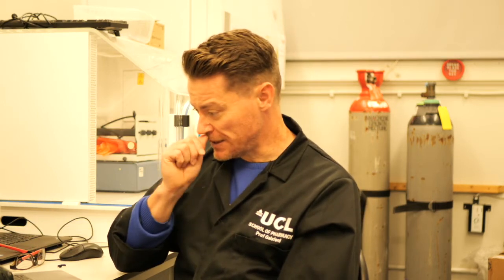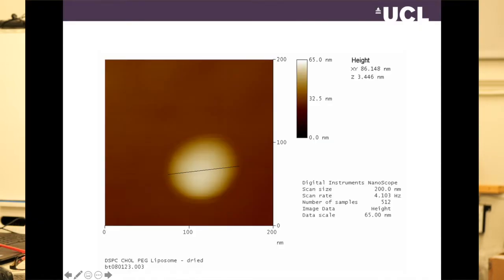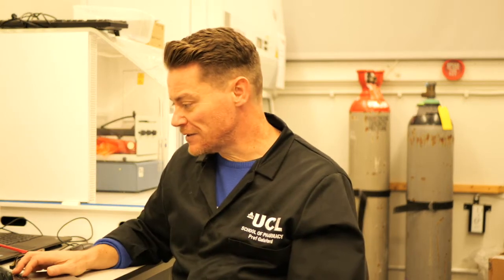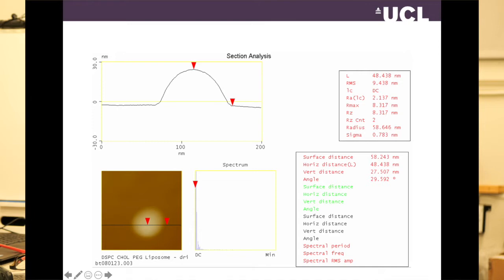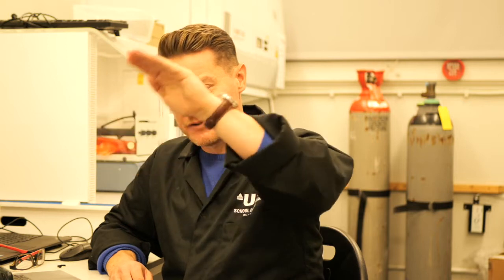You can see that the majority of that topographical image, so that's an X and Y on the image, it's all brown, which essentially means the tip's at a zero, null position, it's at a baseline position, except for where the circle is, where this liposome is, and you can see yellow moving to white circle, which kind of indicates that there's something there. One of the beauties about atomic force microscopy is that the images you're presented with are these grids, and so it's possible to use software to have a little analysis of that sample. So in this case there's a black line going across that circle, and that's part of the software. You can put a line across various parts of the image, and you can ask the software to plot just the Z dimension. So if you do that on the next slide, this is the Z dimension for that liposome, and you can see the tip was essentially at zero and then went over that liposome. So you start to get a real idea for what's the physical size of these individual liposomes. It's kind of scary, the resolution you can get down to with an AFM.